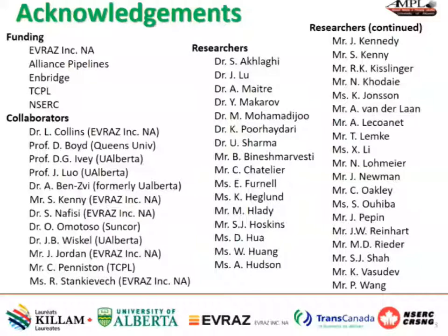They're experimental grades. They're experimental tests. They weren't done for qualification. They were done mainly to see what the process parameters might be for rolling and for cooling, to allow EVRAZ to find the window of processing those. And they've done the processing of X100 in the plant, and I think they have about 2 to 5 kilometers laying around Ottawa as a test line. But those three steels were experimental steels, not production steels.